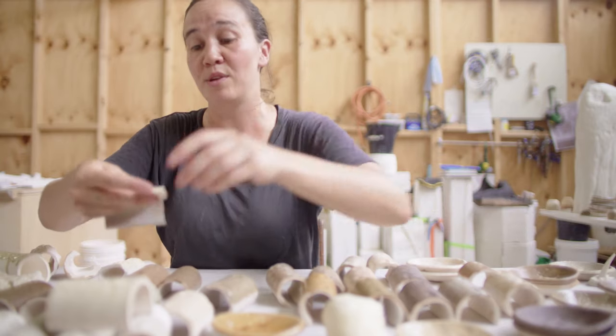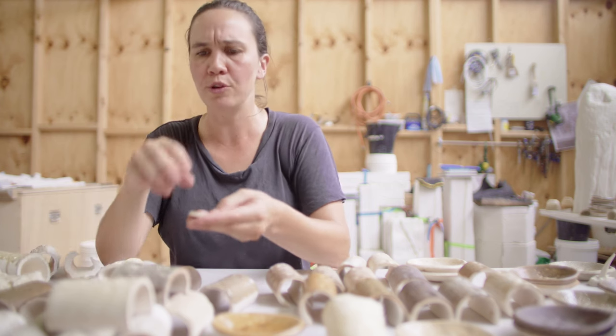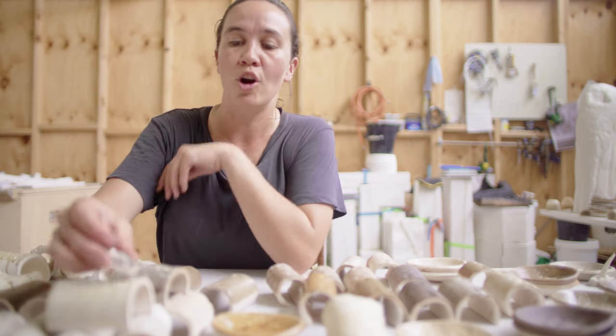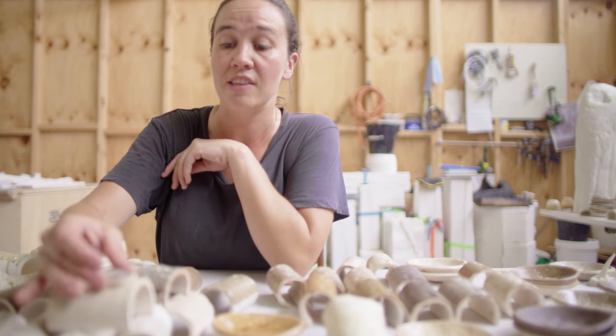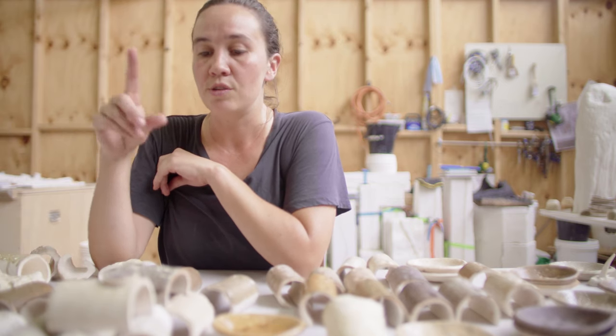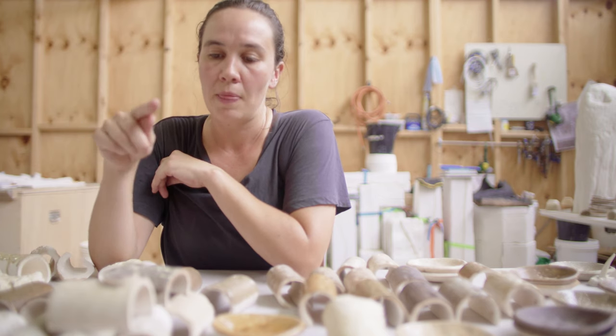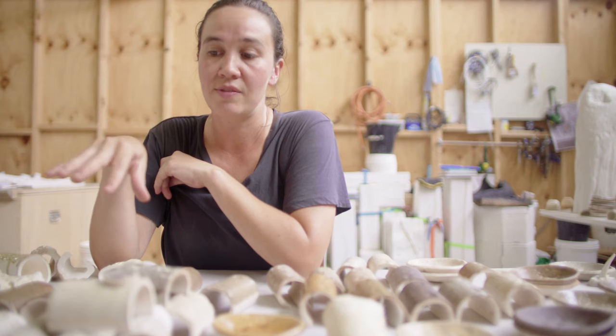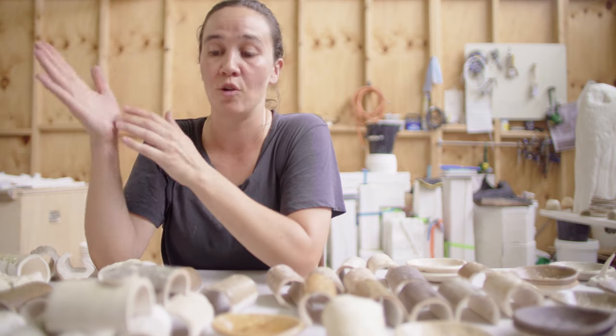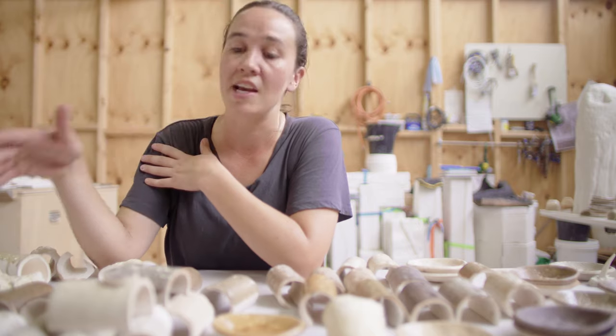That was an interesting story, because when I got the glaze results back from that work, and I thought it looked like a copper green, I went and asked the farmers why there'd be more copper in that tree. And he told me that until about the 1970s, they used to spray this tree with copper oxide to make the fruit go brown. They stopped it in the 70s, but that orchard was actually 150 years old. So it was subjected to almost 100 years of being sprayed directly with copper oxide. And that was just retained in the wood.